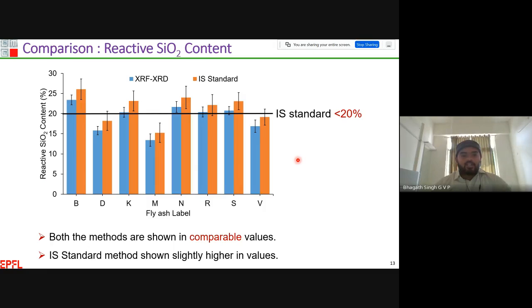This is one of the comparisons of the reactive silica content between our existing methodology, the IS standard, and our XRF XRD technique for all these fly ashes. As you can see here, both methods show more or less similar results with a little difference. For all these fly ashes, the IS standard shows a slightly higher value, because in the IS standard methodology we are using the acid technique. Some of the particles are very sensitive to the acid, and these particles may dissolve. Also, during this methodology, some of the sample may pass through the filter paper, and some of the sample may be retained on the filter paper. All these factors we have to consider while using the existing acid-based technique.